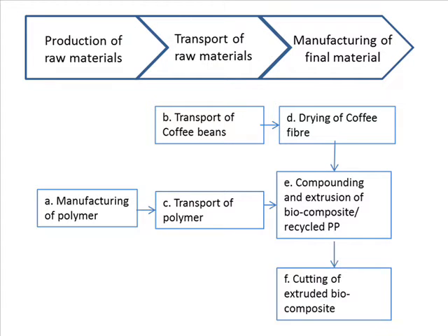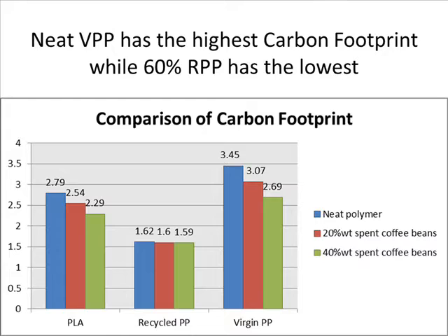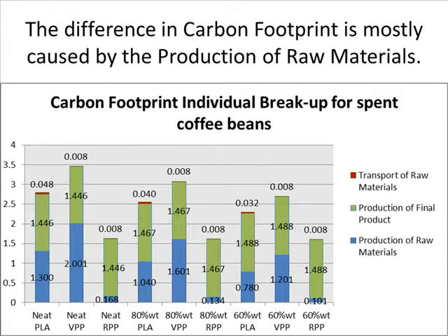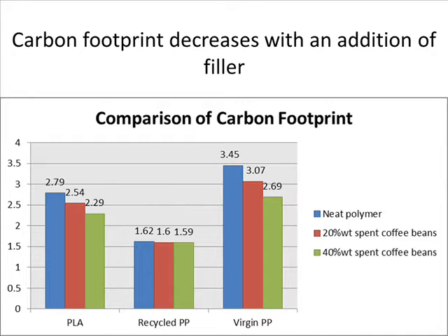Based on the results obtained, the bio-composite made from virgin polypropylene has a higher overall carbon footprint, as its embedded emission due to production process is the highest. On the other hand, as recycled polypropylene was collected as waste, the carbon footprint attached was minimal. Although results showed that the recycled polypropylene had the least amount of carbon footprint than polylactic acid and virgin polypropylene, the difference with the addition of the filler material was much less with recycled polypropylene than polylactic acid and virgin polypropylene. Results show that with an increase in the composition of natural fiber, the carbon footprint is reduced.